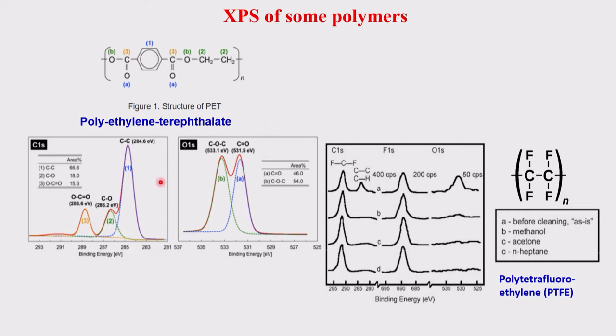For the carbon 1s spectrum those additional peaks can come from other processes. Now for the oxygen spectrum — how many different types of oxygen are there? There is one oxygen attached to two carbons by single bonds, and one oxygen attached by a double bond to carbon. So the oxygen spectrum is simple: you get two types, A and B. A comes around 531 eV and B around 533 eV — a difference of about two electron volts.